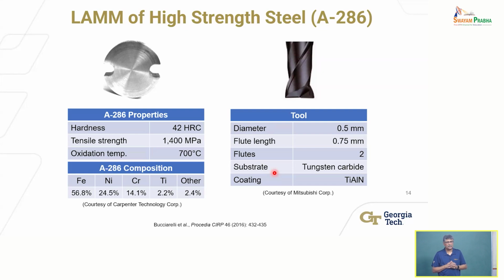And nickel, as you know, Inconel is a super alloy that is used for jet engine turbine blades in the hot section. So these properties are going to be like that. This particular steel is like stainless steel. Its hardness may not be very high, 42 Rockwell C, but tensile strength is high. It does oxidize at 700 degrees C. Obviously, if you're adding thermal energy, you can promote oxidation. Oxidation happens much more easily at elevated temperatures and so on and so forth.